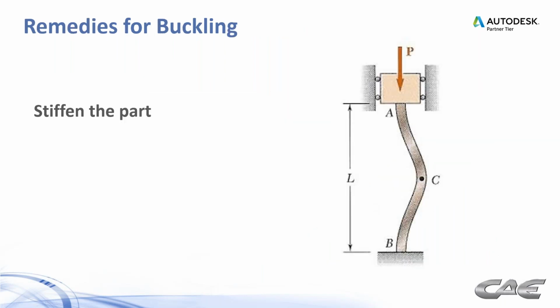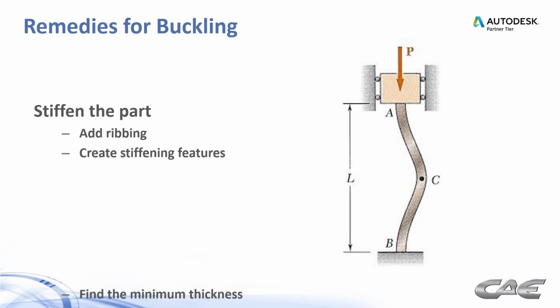So what are some of the remedies for buckling? You can stiffen the part by adding ribbing. You can create stiffening features like corrugated surfaces, things like that. And one of the things we found is sometimes it's an increase in thickness. We're all about thinning walls out, but at some point, you have to find the minimum thickness that you can go to before things start buckling.